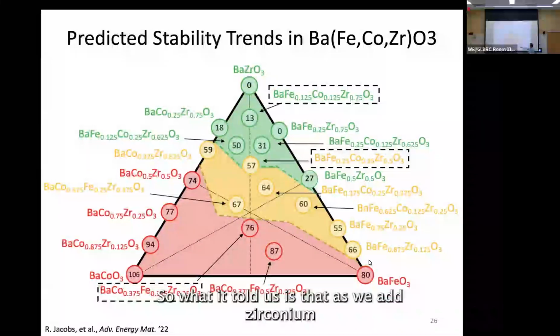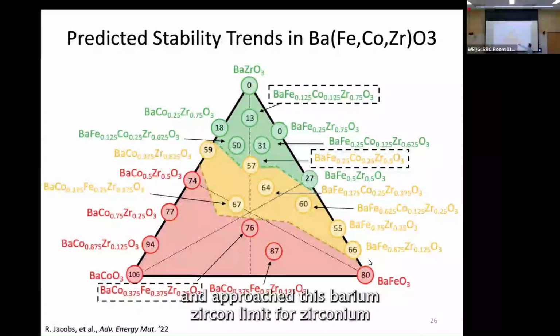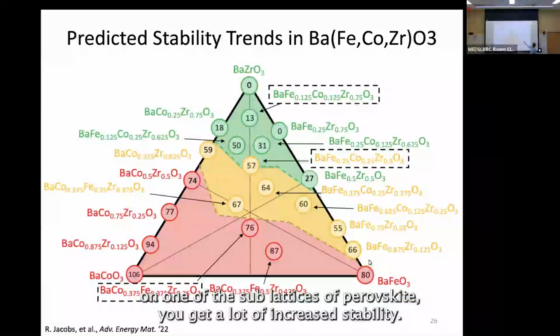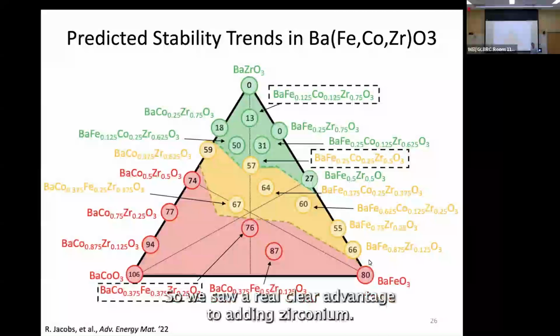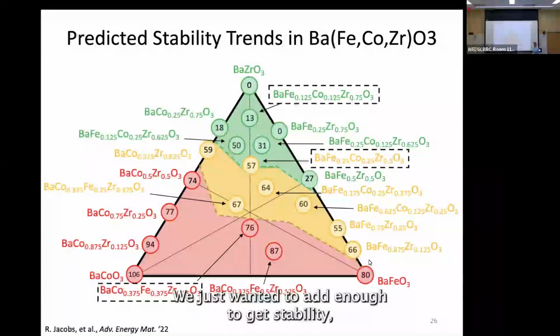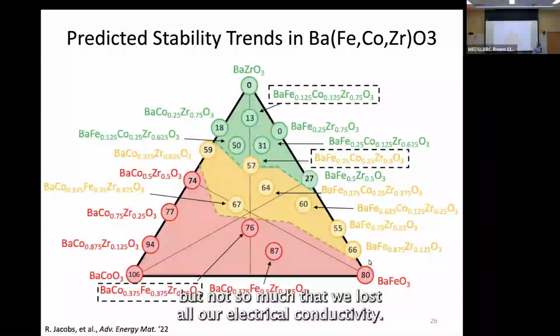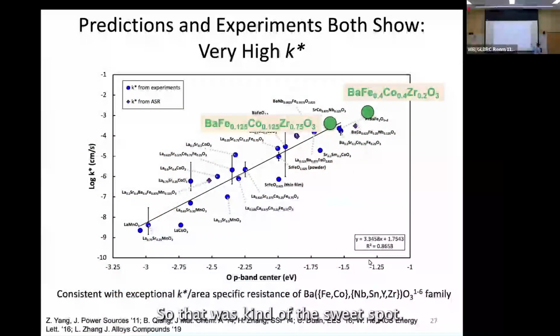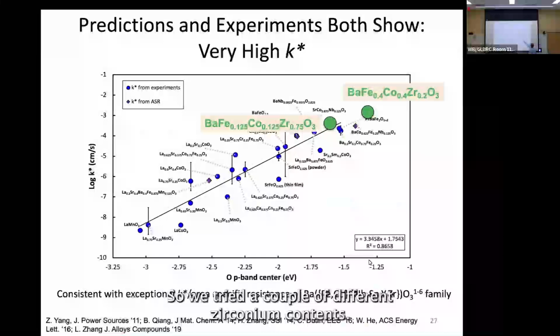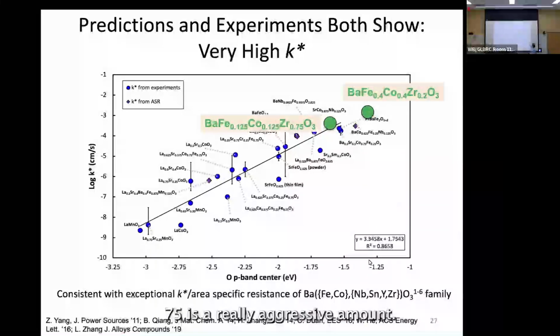So what it told us is that as we add zirconium and approach this barium zirconate limit, with zirconium on one of the sublattices of the perovskite, you get a lot of increased stability. So we saw a real clear advantage to adding zirconium. We just wanted to add enough to get stability, but not so much that we lost all our electrical conductivity. So that was kind of the sweet spot. So we tried a couple of different zirconium contents. 0.75 was a really aggressive amount. 0.2 was a much less aggressive amount.